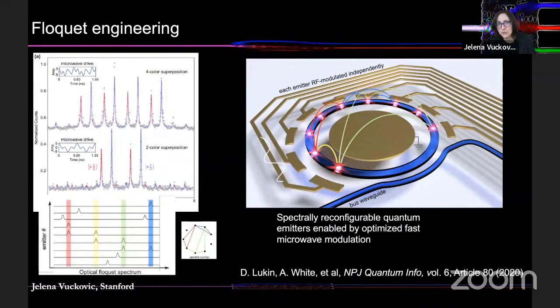We also recently looked into using these electrodes and applied microwave fields for Floquet engineering, kind of going beyond just simple Stark shift, in this case for color centers in silicon carbide, but instead engineering the microwave drive on the color center in order to engineer the spectrum. And this is a drive that contains a few different harmonics, but we've also shown that we can optimize that drive and completely change the spectrum at the output.